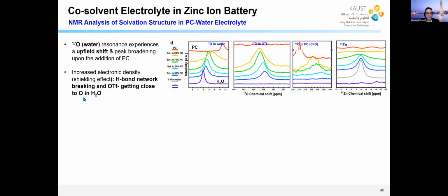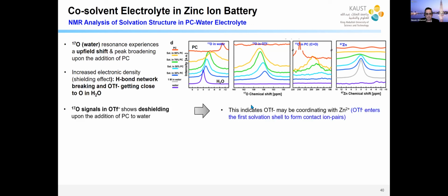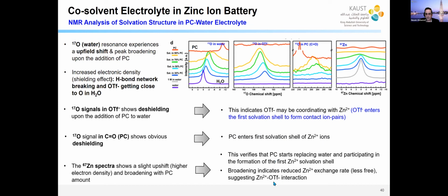Normally, this upfield shift means we have a shielding effect, basically putting more negative charge around this nucleus. This negative charge means we are disrupting the network, and we're putting OTF, which is negative, close to the water oxygen. You can also look at the O17 in the OTF itself, and you see we actually have the opposite: a downfield shift. This is called deshielding, and it is basically a result of the OTF being coordinated with zinc, bringing positive charge around it. So all this data collectively shows the same trend: the OTF and the PC are coming closer around the zinc, and the water is being expelled.